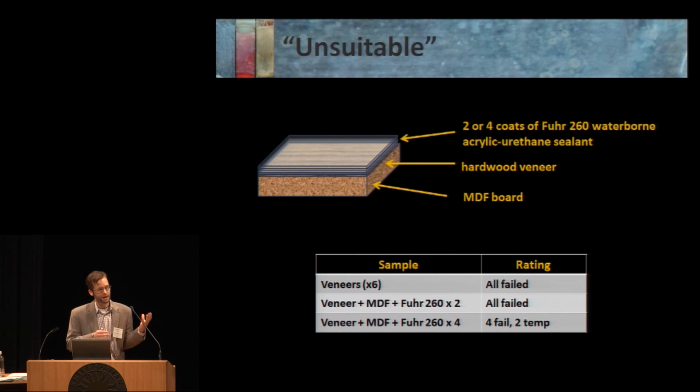The decision was made to allow the veneers, but we were going to monitor these cases very closely. Polished lead dosimeters were included, and if they began to show any corrosion, then we would have to think about actively filtering these cases or perhaps going in and removing those veneers and replacing them with something far more benign.